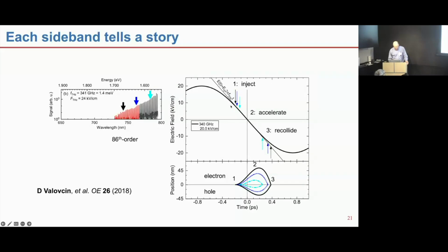And notice that during the part that's associated with the sidebands that we can observe, this is approximately linear. For those of you who know a little bit about higher harmonic generation, there's a plateau with a cutoff frequency. For us, that cutoff frequency would be way, way beyond what we can measure. The ponderomotive energy is enormous here, and scattering is preventing those longer trajectories from contributing.